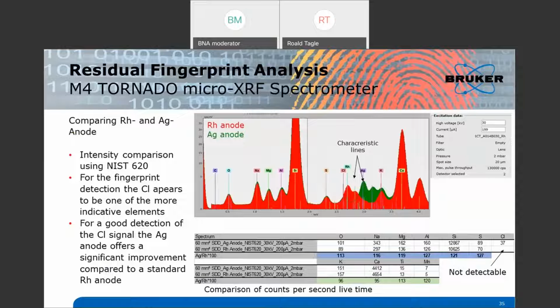So here you see a more quantitative means of comparing the silver and rhodium anode as means for detecting chlorine in a sample. So we have a spectrum of a different NIST reference material. It's NIST 620 soda lime glass. And so there's a comparison of the detected count rates with these two systems, where the measurement conditions were exactly the same.